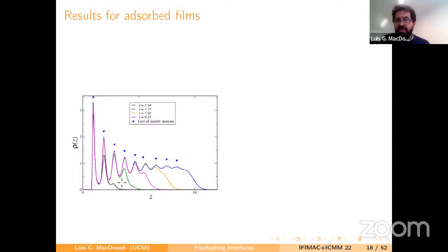I presume that we averaged over all directions, and so our surface tension is actually an average of stiffness coefficients. But notice that these are argon atoms, so the likely structure is close to metallic, close to a solid crystalline structure, it should be close packed. And in close-packed geometries, the anisotropy is rather small. Okay, thank you. Thank you, Olivier. Any other question?